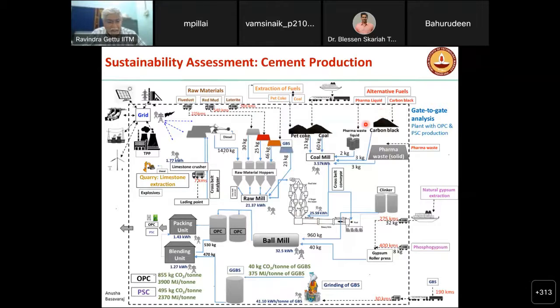So alternative fuels are used extensively in Indian cement plants, and we have to take that into account. All this is mixed together, heated to get the clinker. Then the clinker is mixed with gypsum in the ball mill, crushed, and we get ordinary Portland cement. And if you do all this process, you can come up with some numbers. At the bottom here, you can see that the carbon footprint in this particular case of 1 ton of ordinary Portland cement is 855 kgs.